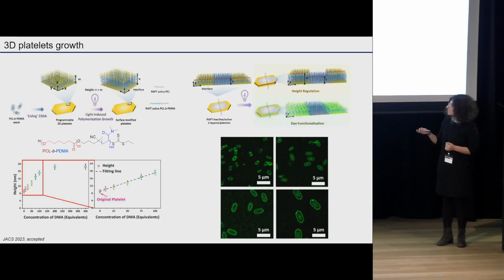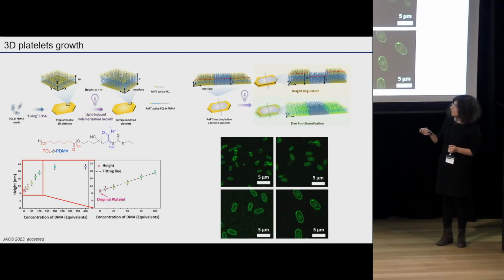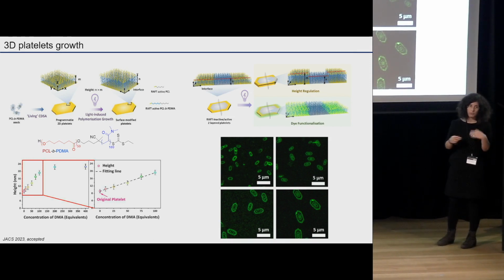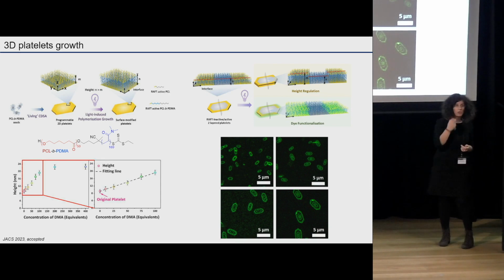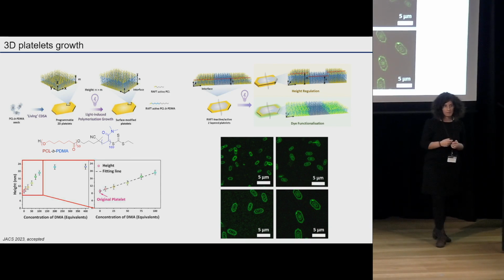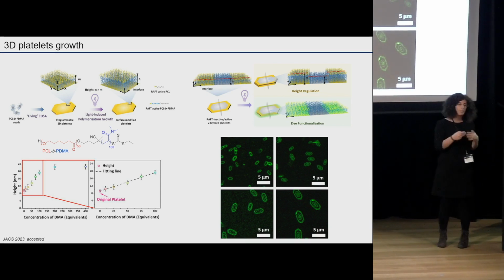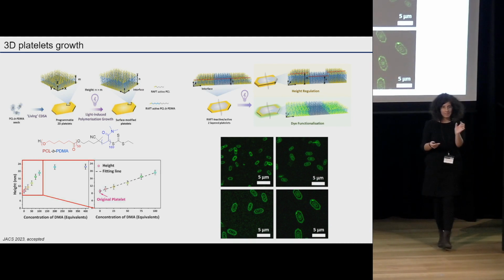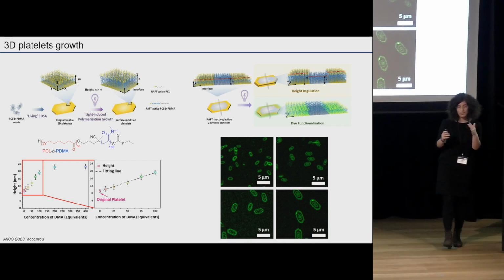And not only this, we have great control over the growth in 3D, as you can see here, so it's directly proportional to how much monomer we add. But also, we have great control over the location of the growth as well. And so you can, for example, in a nanoparticle, select a specific region that you want to grow, and then you can grow just that specific region without touching the rest of it. So you have great control over the location that you introduce your functionality in.